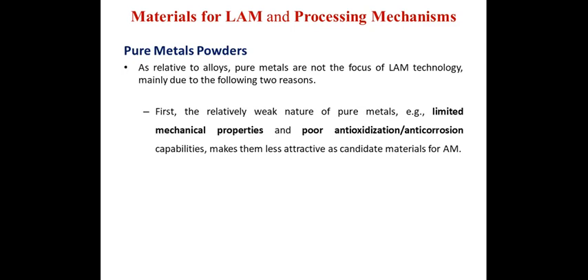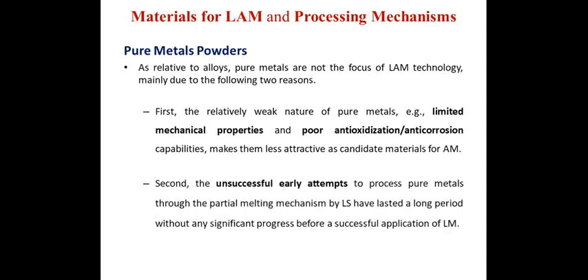One is the relatively weak nature of pure metals. Limited mechanical properties and poor anti-oxidization or anti-corrosion capabilities make them less attractive as a candidate material for additive manufacturing. And the second reason is that unsuccessful early attempts to process pure metals through the partial melting mechanism by laser sintering went a long period without any significant progress before a successful implementation of laser melting.